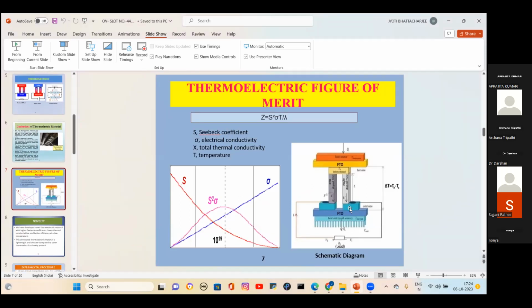And this is the schematic diagram of my experiment. I have used the P side and the N side. In the P side, I have used silver telluride doped reduced graphene oxide. And in the N side, I have used bismuth telluride doped reduced graphene oxide. My substrate is fluorine-doped tin oxide (FTO) glass. And I have used the heat source from above and cool water from below the FTO, which I have used as a cold source.